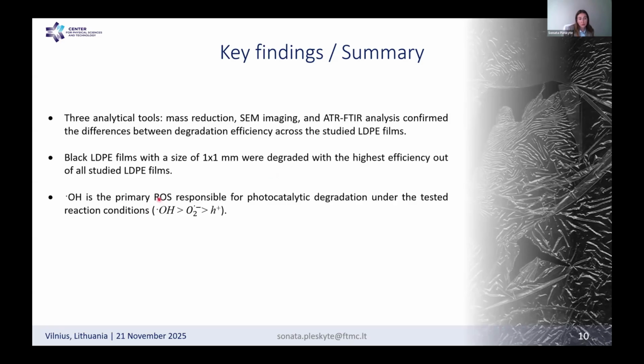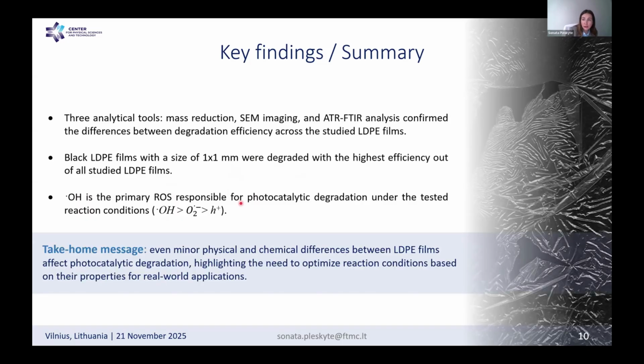And also we found that black LDPE films with a size of 1 by 1 millimeter were degraded with the highest efficiency, which was approximately 9.8%. And finally, we found that the hydroxyl radical is the primary reactive oxygen species responsible for photocatalytic degradation. And you can see the order according to their impact and influence on the degradation efficiency. The take-home message would be related to physical properties. I want to highlight that even minor physical and chemical differences between LDPE films can affect photocatalytic degradation, highlighting the need to optimize reaction conditions based on their properties for real-world application.